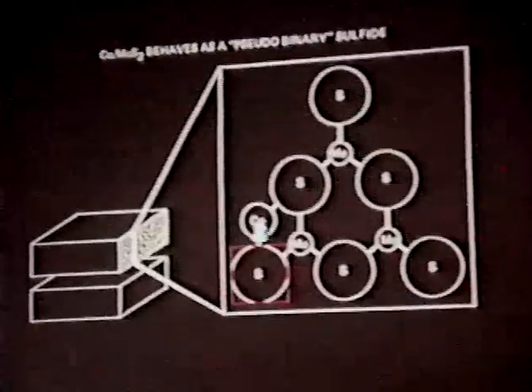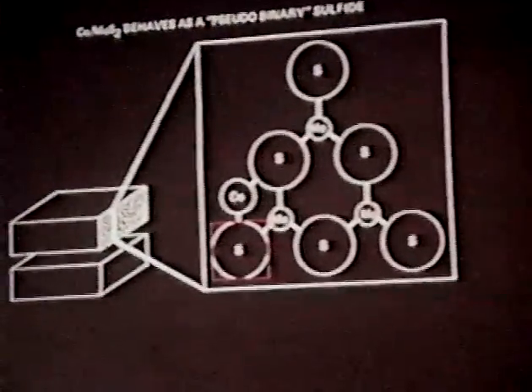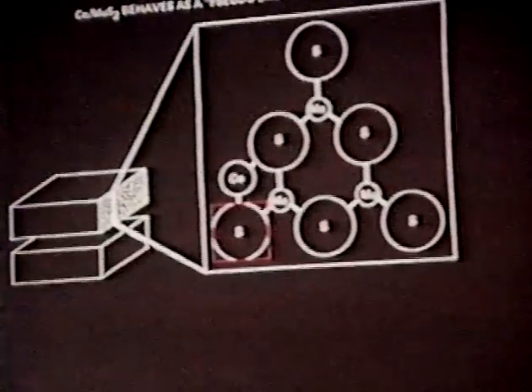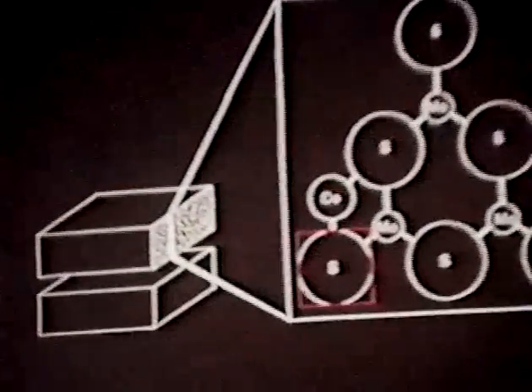We're at a period of time now where the controversy is welling up again about what this structure is. I'd like to make some suggestions for argument's sake. Having known this information a number of years ago, we proposed that the way these catalysts work is, in effect, to have a vacancy bound between cobalt and molybdenum. What this will do is average the property of those vacancies.